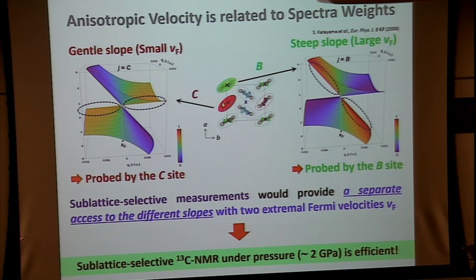But this C molecular orbital does not show a sizable contribution to the steep part. So if we do site-selective carbon-13 NMR, which probes the electronic state separately at each molecular site, we can know the local spin susceptibility here and here. And anyway, if the Dirac cone is preserved in such a shape, the density of states is like this.